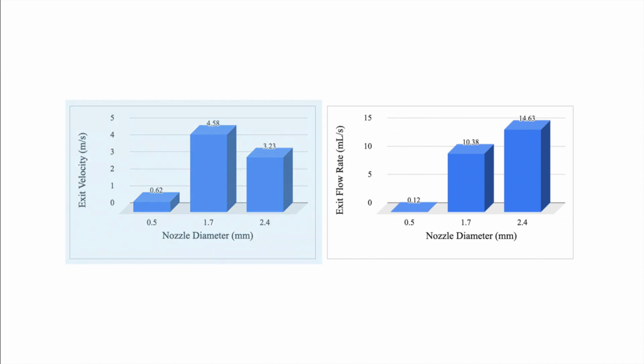For instance, exit velocity sort of has a maximum in the mid-range of diameters, and this is because on the lower range of diameters, say 0.5, the viscosity actually is the limiting factor that restricts the nozzle velocity. However, on the higher end, increased cross-sectional area for a given flow rate is the limiting factor that causes the outlet velocity to be reduced.